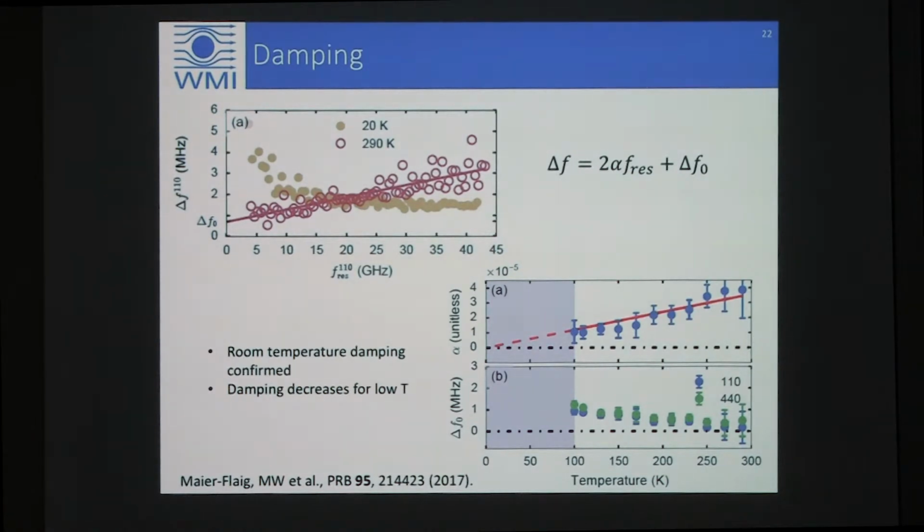Okay, so meaning once you single out this relaxation with the rare earth impurities, then actually the damping decreases. And that means if you want to do some things like cavity spintronics, strong coupling, at high enough frequencies, then cooling down actually helps you, right? It doesn't help you if you have a cavity at 5 gigahertz or something, because your line width is going to increase due to the slowly relaxing impurities. But if you're out here at 50 gigahertz or somewhere, then cooling down should actually improve things.